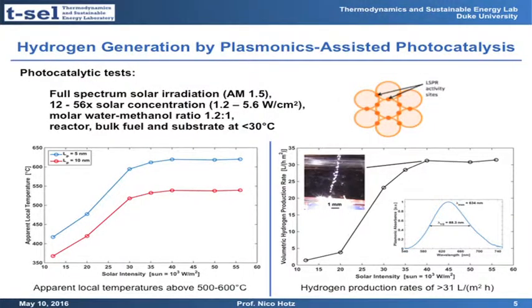So we use it under full spectrum light. We concentrate it with a moderate solar concentration of 12 to 56 times. It's with a very cheap Fresnel lens. We put the whole substrate in liquid water methanol, and then we don't heat it externally at all. The whole reactor, the fuel, the substrate, everything is below 30 degrees Celsius, so very cold. But locally, apparently, we can achieve temperatures above 500 up to 600 degrees Celsius, depending on the size of these